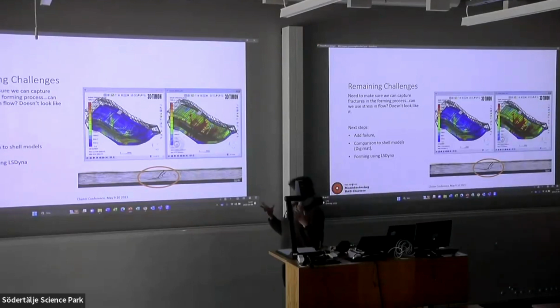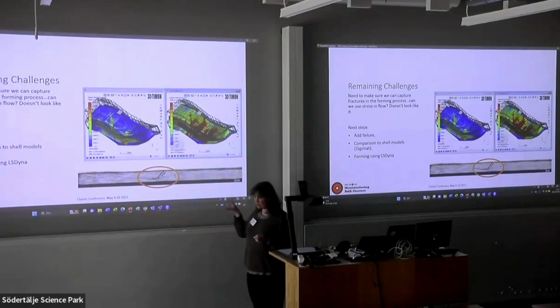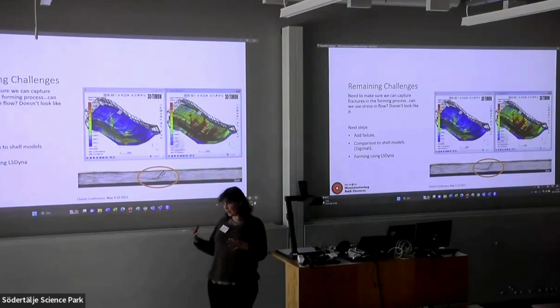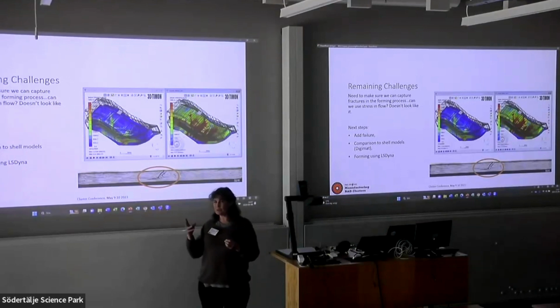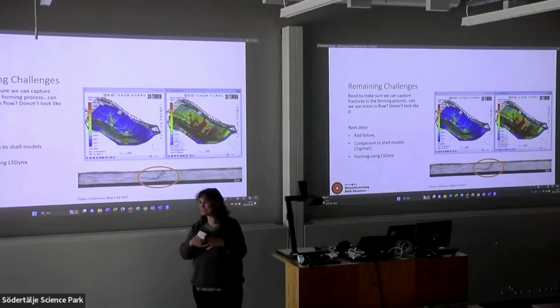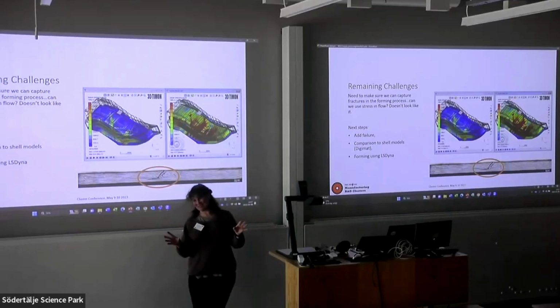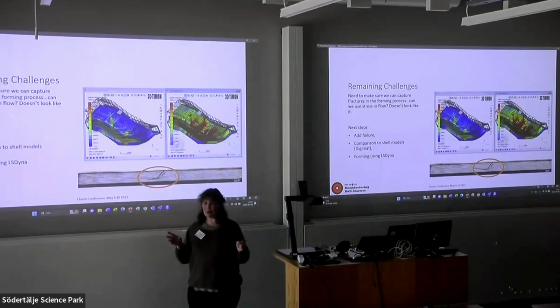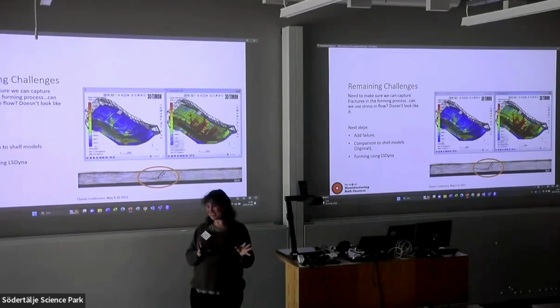There are different ways of going. One is that there is a chemical process that we can use with a thermoset to break it down. But that was the most complicated of the plastic solutions that Matthias presented this morning, where you use chemical recycling and break it down. But you don't have to go down to the monomers. Well, actually, probably. Anyway, you can get some really good fibers from that. That works really well. And pyrolysis also works nicely with carbon fiber. Unfortunately, it doesn't work very well with glass fibers.